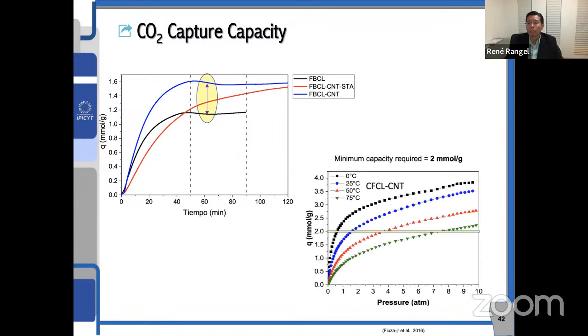That's very important. Well, now, if we apply pressure, you can see that the material that has the carbon nanotubes increases the capture capacity of CO2 quite a lot. Even at 10 atmospheres, which is not a very high pressure, we already have a capacity close to 3.5, 3.7 millimoles per gram. Now, it has been established that the minimum capacity required for an adsorbent material is 2 millimoles per gram. So we are already above that capacity, and we are very happy about that. We just submitted this data. These are quite new and I think quite important.